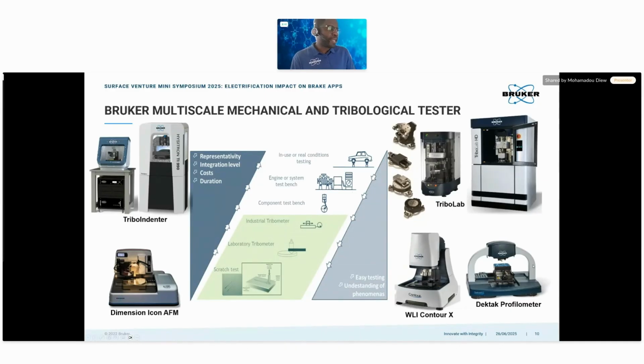But before this, you have optical profilometers to characterize the roughness of surfaces before and after the testing, to be sure of what really happens and how we can describe the wear mechanisms in this configuration of testing that we run. You can also go to a lower level, for example AFM, if you see on the secondary plateau some generation of powders, to characterize these powders and to know better what their structure is and if they can help to build a picture of what is really happening in the contact that generates these particles.